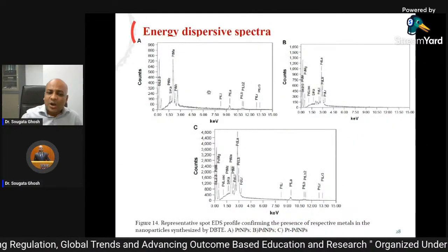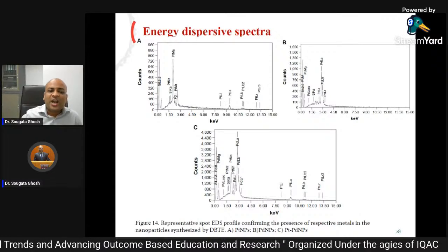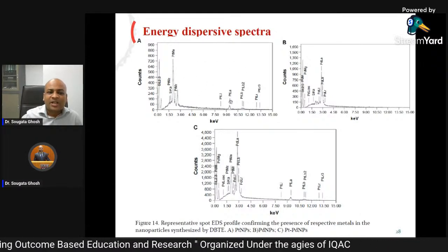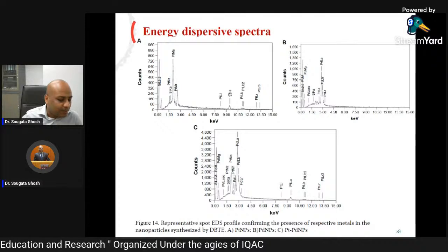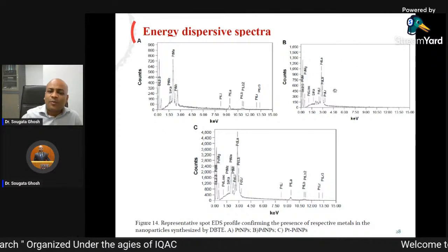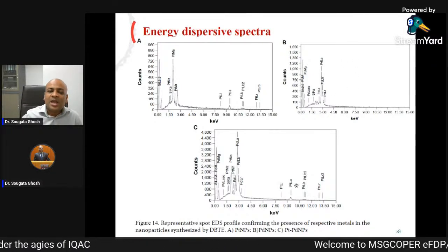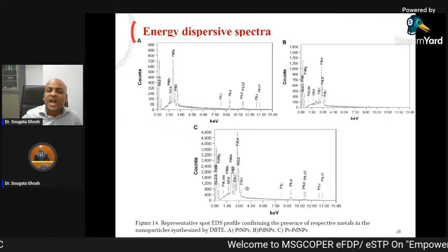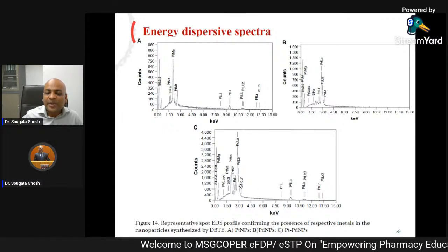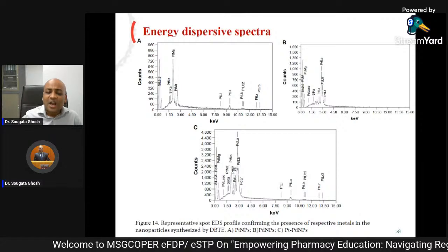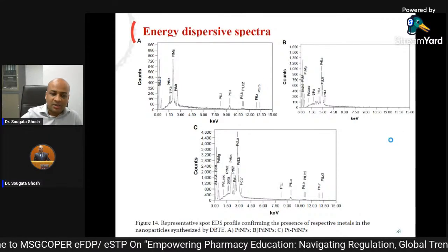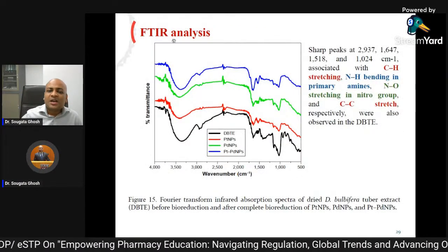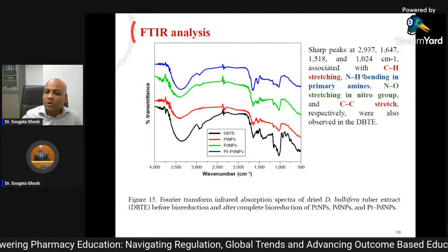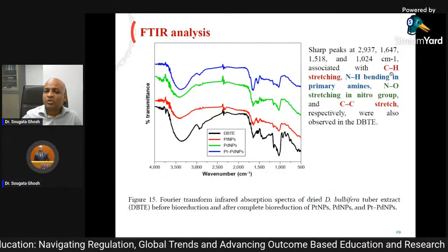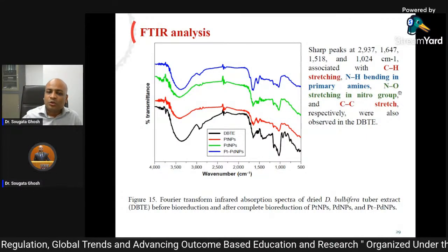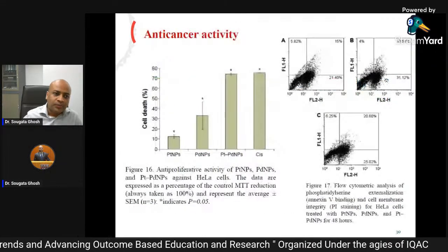So we found those nanoparticles were indeed made up of platinum. See, this is the platinum nanoparticle, and you can see the Pt peaks, platinum peaks. This is the palladium nanoparticle, you can see the Pd peaks. And in this, you can see both Pt and Pd. So that means these nanoparticles have both the elements. Again, FTIR, we tried to find out which groups are playing a role in synthesis and stabilization. So CH, NH, NO, these groups were playing an important role.